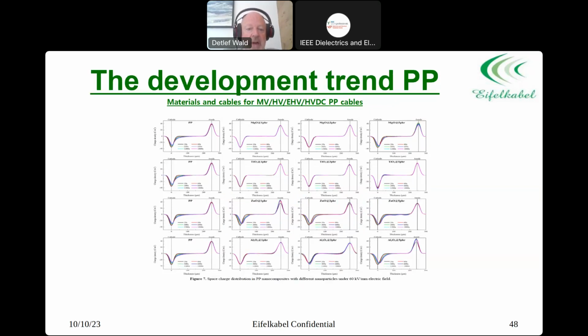So I hope when you're having it there, we're comparing here on the left-hand side polypropylene. The tests that were done here were adding different additives to it: magnesium oxide, titanium oxide, zinc oxide, and aluminum oxide. 1 PHR, 3 or 5 PHR. PHR, for the people who don't know it, is parts per 100 rubber. This is coming from the rubber industry. So you use the whole total polymer as 100%, and then you just add 1% or up to 5% of the additive to it.